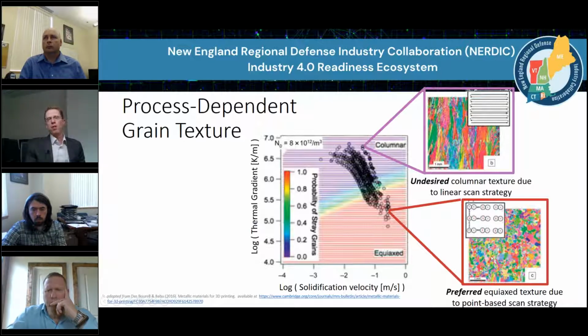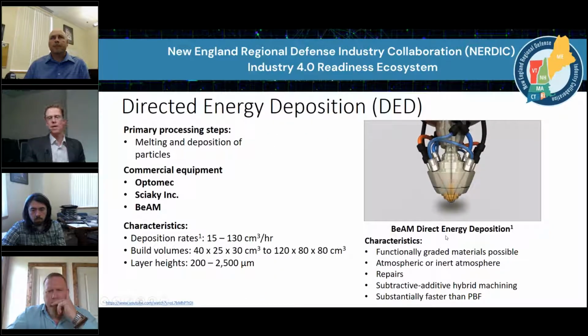The key important thing here is that the process can control how these textures are formed, and columnar grains can struggle in higher order mechanical effects like fatigue. So if you're making aerospace aircraft structures, you probably want to avoid these columnar grains up here, and you want to focus on producing these equiaxed grains on the lower right.